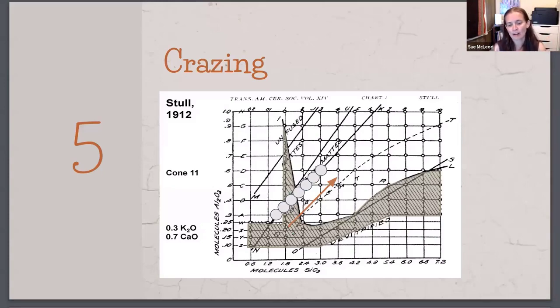If your glaze is crazing and it is in this lower crazing region of the Stull chart, one test you can do, no guarantees, is to increase silica and alumina to move up and to the right, keeping the ratio of silica and alumina the same by way of UMF. And that is one simple way to try to reduce crazing.